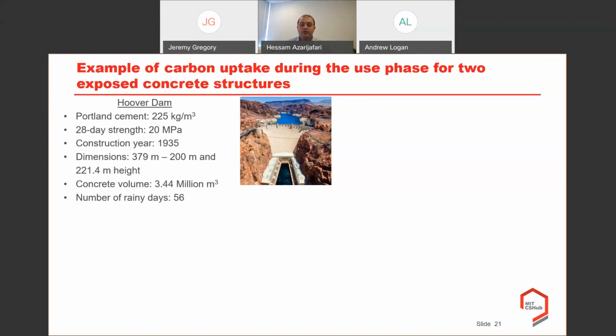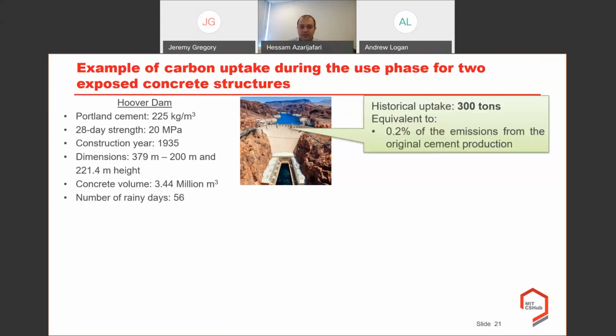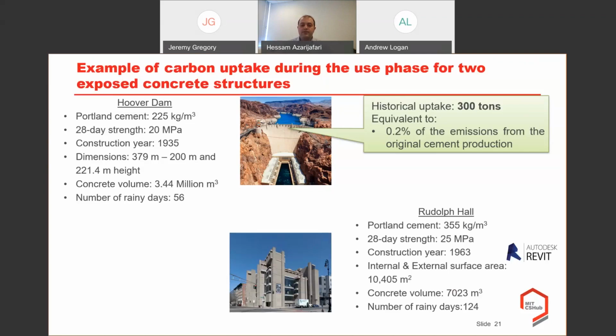concrete used for this. For the number of rainy days, we assume that on those rainy days the concrete is totally saturated, so the relative humidity is 100% based on this assumption. And we observe that the historical uptake up to now, the concrete carbon uptake, is around 300 tons, which is equivalent to 0.2% of the emissions coming from the original cement production in 1935. So this is one example.